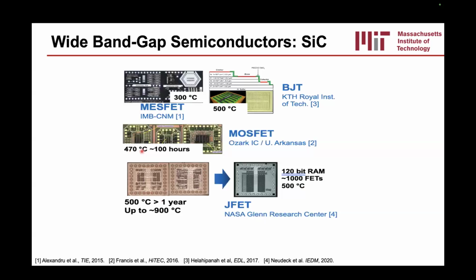There's been a lot of work already on silicon carbide. Silicon carbide is kind of like the older brother of GaN. It's been around for about 20 years more than GaN. And the folks over, especially at NASA, have really pioneered some really amazing work in high temperature silicon carbide electronics. And they're currently at the level where they can demonstrate a small little RAM cell with about 1,000 transistors operating at 500 C. But we think we can do much better with gallium nitride.